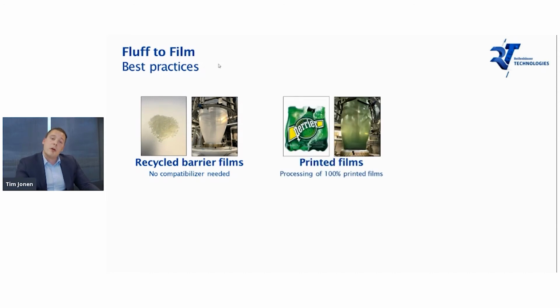Another very positive example that I would like to present to you is the processing of heavily printed films. Like you can see on the picture, we've done numerous trials with heavily printed films that had up to 100% of printing or ink on the film. Especially for printed films, we could see that the benefits of the degassing units are second to none, giving us the chance to degassify any inks out of the film, ending up with much higher and much better film qualities and properties.